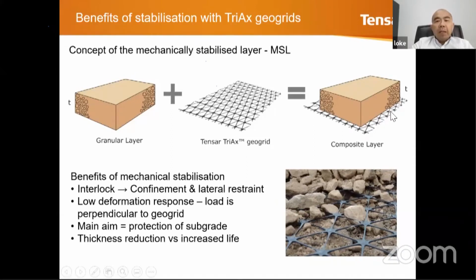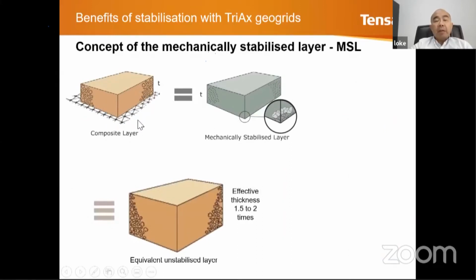Okay, so by putting a layer of geogrids, you can see that the layer at the bottom here will be interlocked. It can't move. Stiffness is there. Stiffness is as good as original. When there's no movement, so again, back to the definition of stabilization, when you have got limited movements, no deformation of the stones at all, you can see the movements in the Penn State University's video. When there's no movement at all, this whole material is very rigid. And therefore, you have got minimum deformation. All right. So when we use this, we can actually save a lot in terms of construction time and also material cost. Instead of using a layer which is 1.5 or 2 times thicker without any geogrids, we can use a layer which is thinner, half the thickness, and it performs much better by giving you a better number of traffic passes.